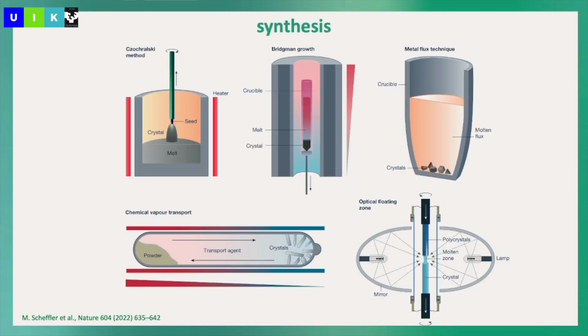So what we now need to grow are these crystals, and these are simply giving you a little bit of an impression. We have many different growth methods, some where we simply take a tiny little crystal in a melt, and then we grow the crystal larger and larger. This is a very well-controlled way to grow crystals, but sometimes we simply mix something together with some additional liquid. It can also be made by solids, and we hope crystals are grown, if the crystals have a very simple phase diagram. But one method that is very nice also for 2D material is chemical vapor transport. You start with a powder and you have a transport agent and you grow some nice crystals, simply to give you a little bit of an impression.